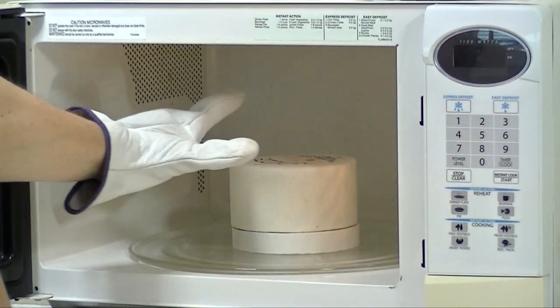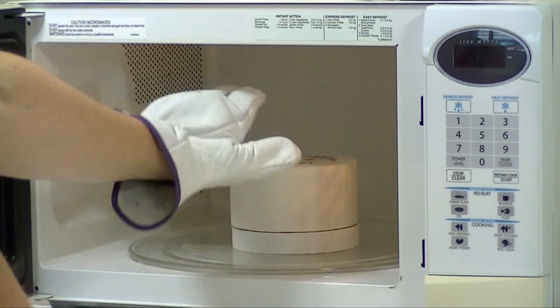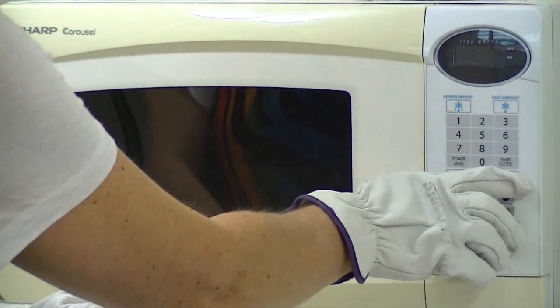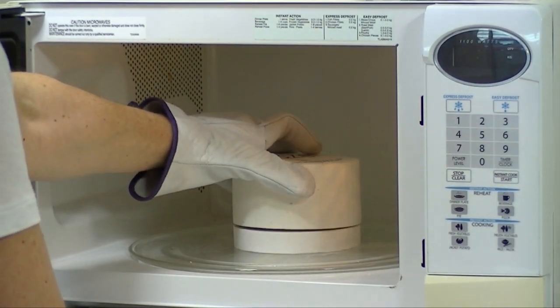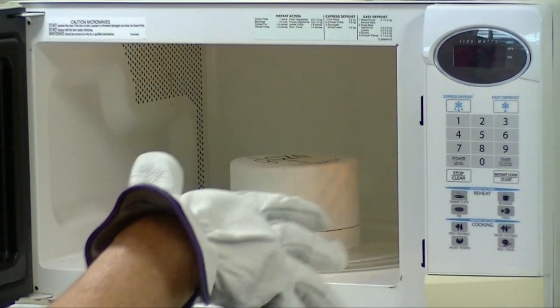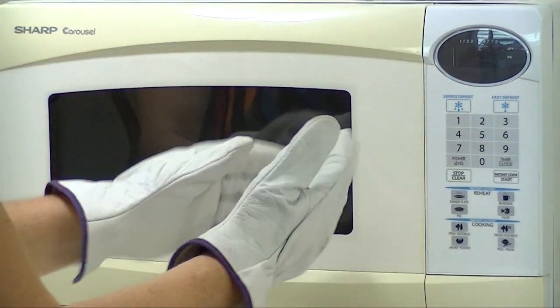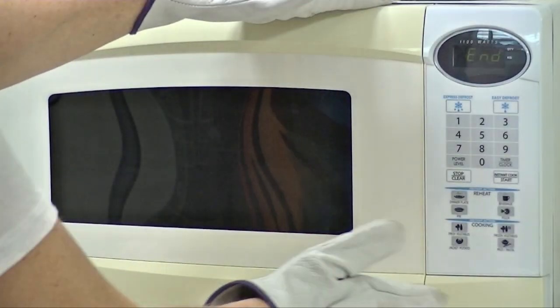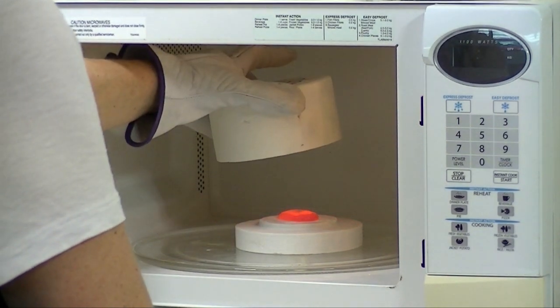Okay, so that's been three minutes on 50%. It's all still in one piece and that's a really good thing. We're going to close the door and now we're going to go for one minute on high. I can see a little bit of a glow coming from here, so it's heating up. Our capping is starting to slump down and our glass is starting to take on an orange shade. So we'll just go for 30 seconds now. Let's have a little look — perfect, looks great.